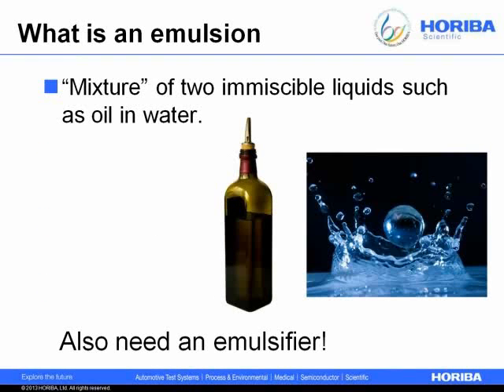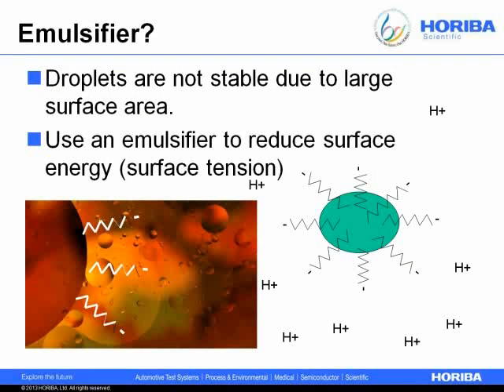An emulsion is a mixture of two immiscible liquids, such as oil and water — the classic picture being a bottle of olive oil and water that you're trying to mix. You also need an emulsifier. If you have droplets of water in oil or vice versa, those droplets have quite a high surface area and a surface energy penalty associated with that area, so the droplets are not going to remain particularly stable. Emulsifiers reduce the surface energy or surface tension. In some cases, one of the phases itself acts as the emulsifier — for example, vinegar stays in oil because it acts as an emulsifier.